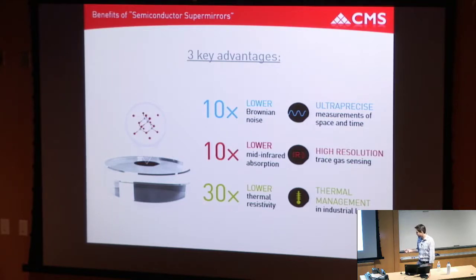And the other point is, because it's a high-quality single crystal structure, the thermal conductivity is quite high. So we're looking at in-plane thermal conductivities as high as 70 to 90 watts per meter Kelvin. You're phonon scattering limited in the multilayer to about 30 watts per meter Kelvin in the multilayer stack there. But compared to a traditional amorphous metal oxide, it's about a 30x improvement. You're looking at a little less than 1 watt per meter Kelvin in a dielectric mirror. So for high power laser applications, specifically CW, there's some interesting aspects to having this combination of low optical losses and high thermal conductivity.